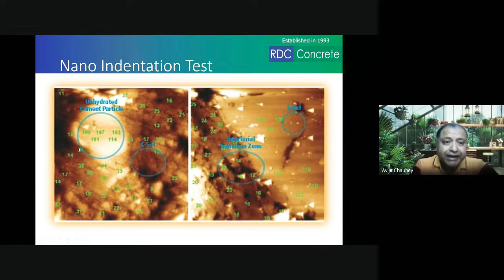Now the interesting thing that you see after 6 months is there is still unhydrated cement particle on the left side of the picture. Around it, the dark color material is the hydrated cement paste, that is nothing but CSH, the calcium silicate hydrate gel. On the right hand side of the picture, it is an aggregate, a sand particle under the microscope, and surrounding it again is the CSH, the calcium silicate hydrate. Now, this test is a nano indentation test, and in a nano indentation test, they measure the strength of that material at that small point.